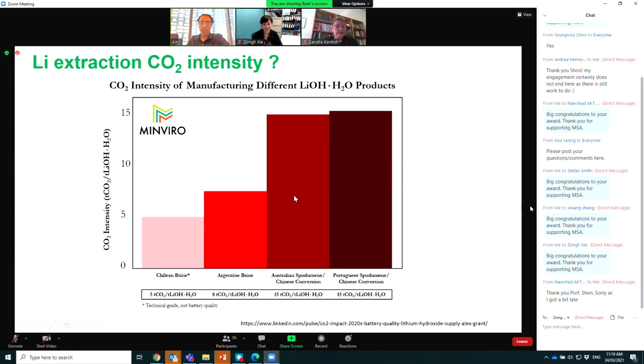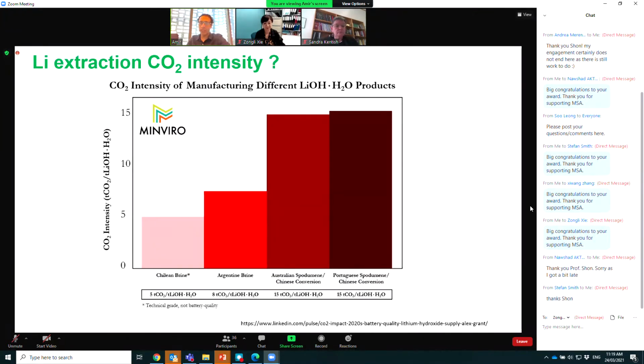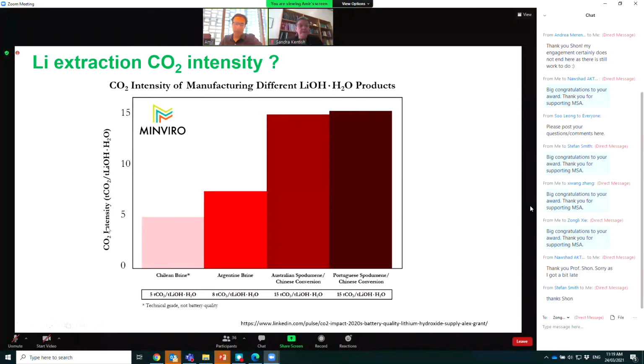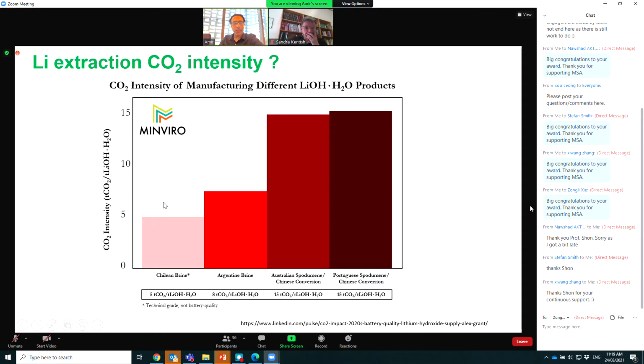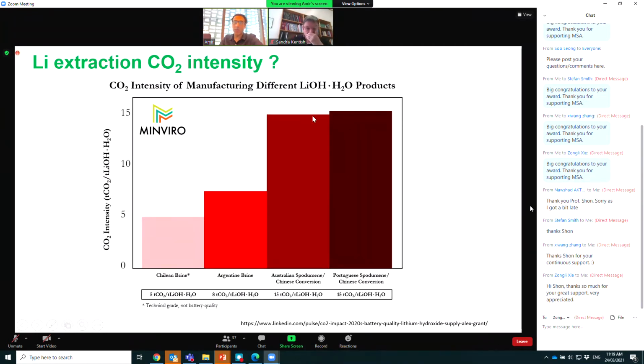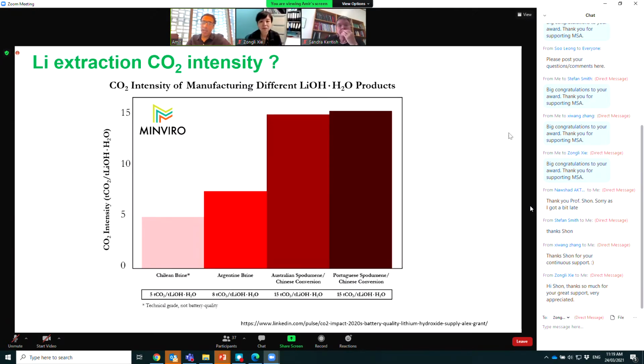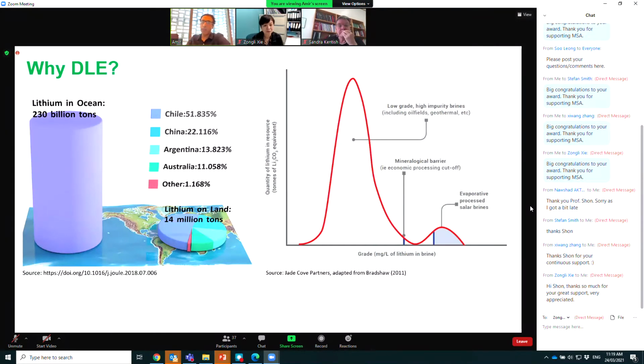The other thing is related to the carbon CO2 intensity of manufacturing different lithium hydroxide products. This is from Alex Grant's life cycle assessment on the CO2 footprint of lithium hydroxide. For brine, 1 ton of lithium hydroxide produces 5 tons of CO2. And when it comes to the mining industry and extraction of lithium from rock, it's somewhere around 14 to 15 tons of CO2. That's a huge amount of carbon we are emitting currently to produce lithium-ion batteries. So keep that in mind. I'll talk about that one soon.